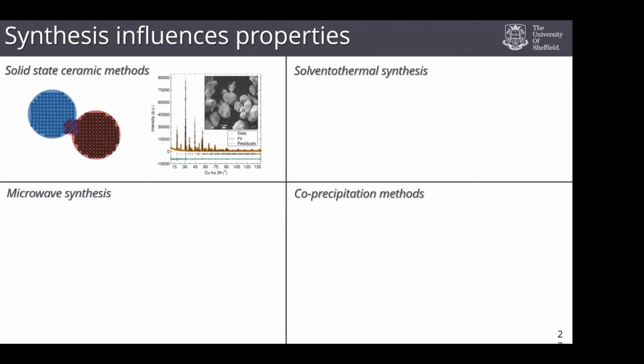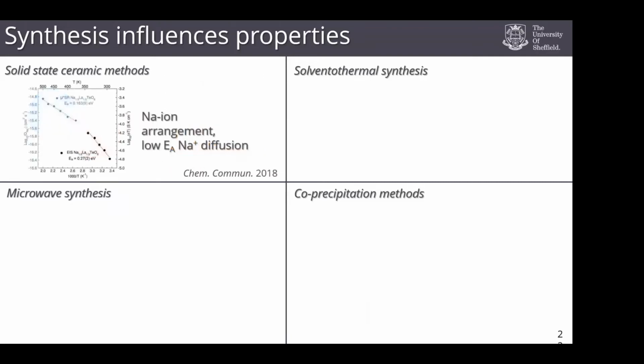And by doing this kind of method, we can systematically change how the chemistry of these materials exists. And in this particular case, we were able to change, in this material, it was a sodium ion electrolyte, so something that allows sodium ions to move through it, but is not a liquid, it's a solid. And by doing that, we can lower the activation energy that sodium ions need to be able to move. So this was really great.